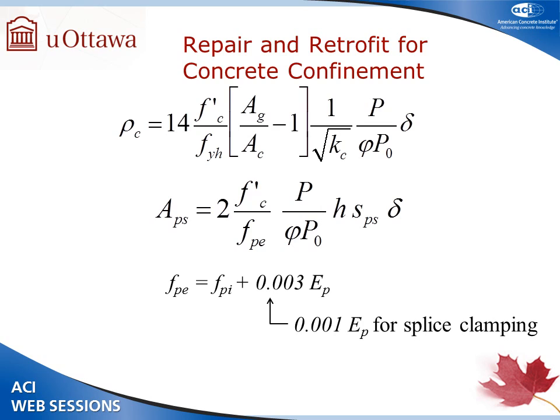And in terms of effective prestressing stress, you can go up to 1860 megapascal, but still concrete is not able to expand that much without failure, and hence we put a strain limit. We observed that transverse strains of up to 0.5% were tolerated by concrete, but we did recommend use of 0.3% so that you would first overcome the initial prestressing, and then you would have zero strain, and then you can go a further 0.3% in transverse tension without failing concrete as it becomes more and more confined.